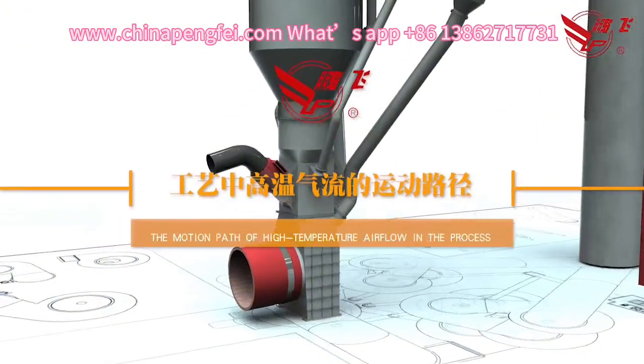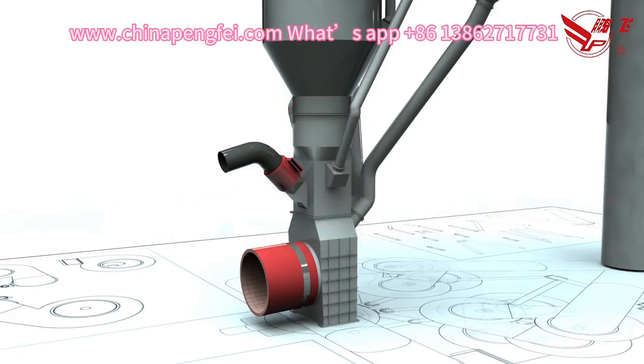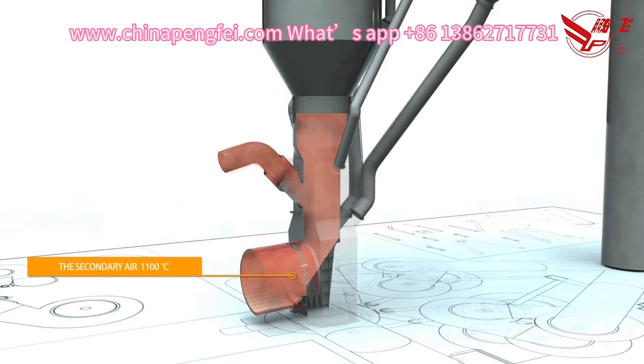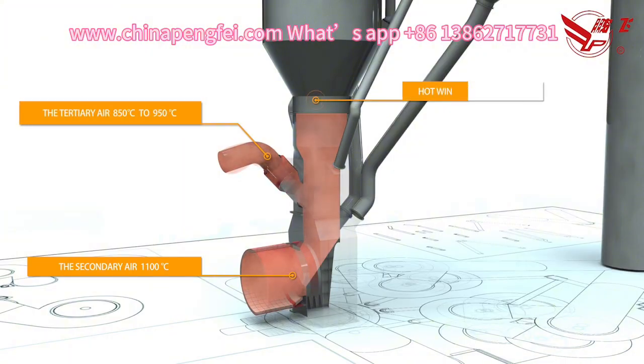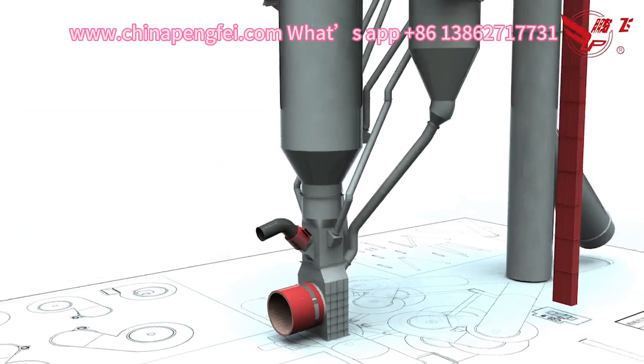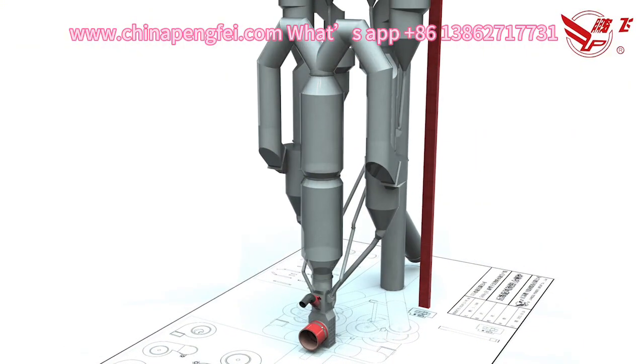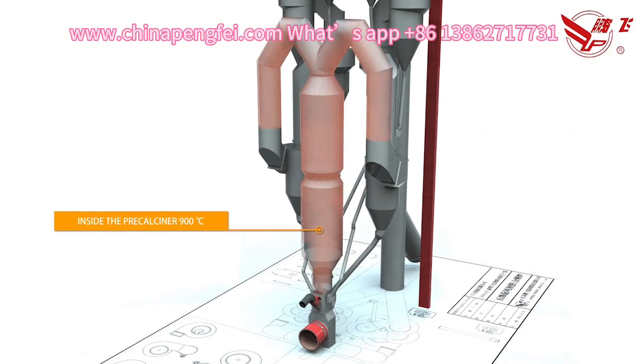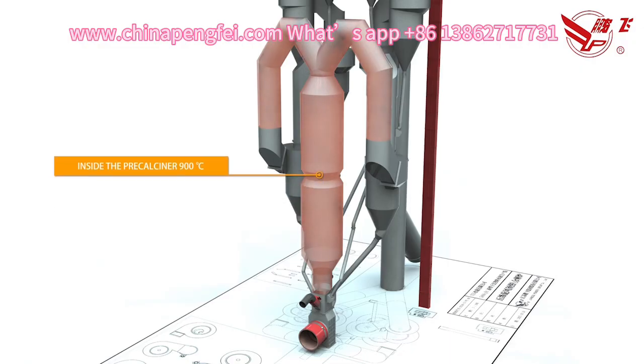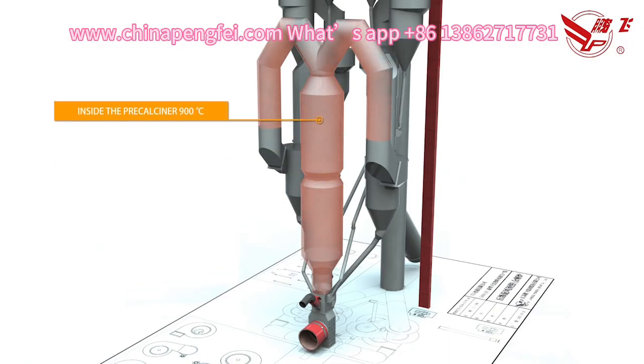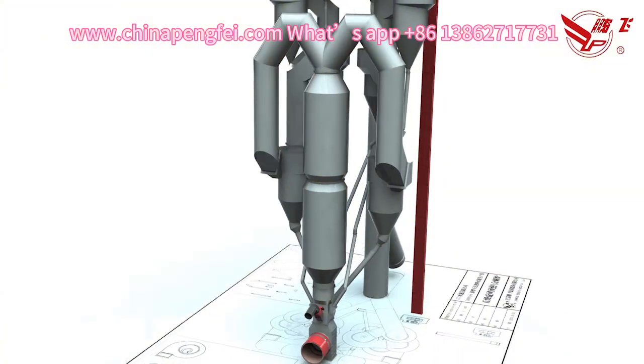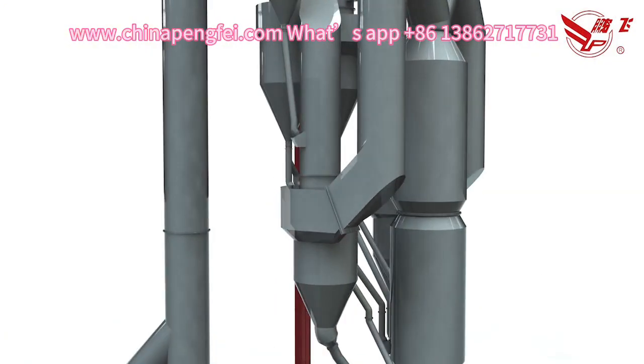The motion path of high temperature airflow is, firstly, the secondary air at approximately 1100 degrees Celsius in the inlet of the rotary kiln, and the tertiary air at 850 to 950 degrees Celsius discharged from the grate cooler enter the pre-calciner. The high temperature airflow in the pre-calciner moves rapidly from bottom to top, at which point the hot air temperature inside the pre-calciner is approximately 900 degrees Celsius. The hot air in the pre-calciner enters the fifth stage suspension preheater through the air duct.